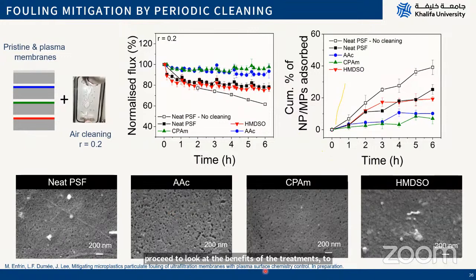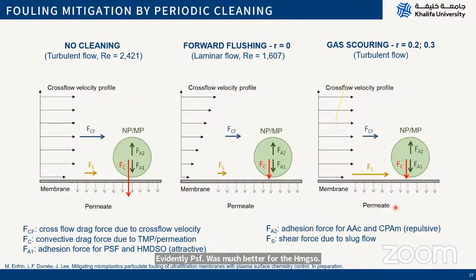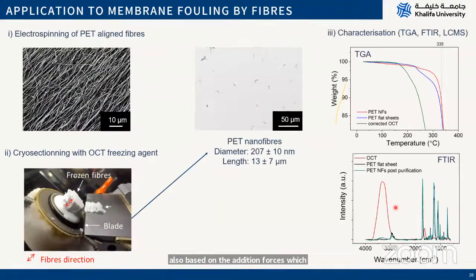So the acrylic acid and the CPAM with the amine groups were much cleaner after air scouring. Even the PSF was much better. For the HMDSO, the silicon base, it was less obvious, but all the others showed significant improvement of fouling behavior over time. We developed different models to explain the behavior based on the gas scouring input ratio, and also based on the adhesion forces between the particles, polymer, and the materials.